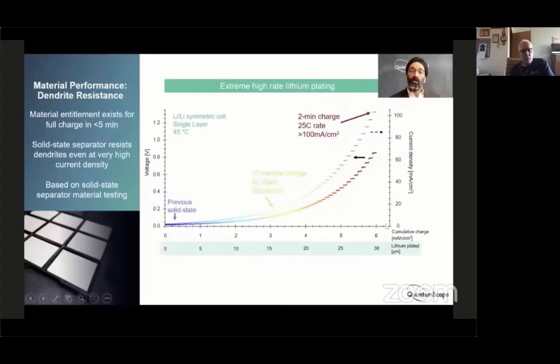To do a fast charge, you have to be up on the order of 15 to 16 milliamps per centimeter squared. And you can see our cell, our material can withstand that with no failures. We then took the current density higher and higher to see how high we could get without seeing failures. And in this case, we were able to get to over 100 milliamps per centimeter squared of current density, which corresponds to a 2-minute charge or a 25 C rate without a failure.